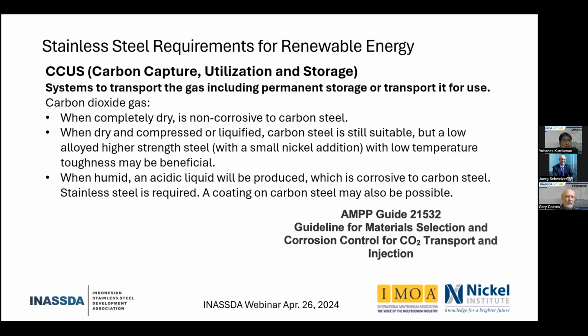higher toughness material. So we add a little bit of nickel for that, but you also add a little bit of nickel to the carbon steel to give it a higher strength, because when it's compressed, you have a pressure there. So you want to use a higher strength steel. Those again are not stainless steels, but they're carbon steels that are optimized to give the higher strength, but the low temperature toughness. And of course, when CO2 gas is humid, you get an acidic liquid, carbonic acid, and that is corrosive to carbon steel, and therefore you need stainless steel.